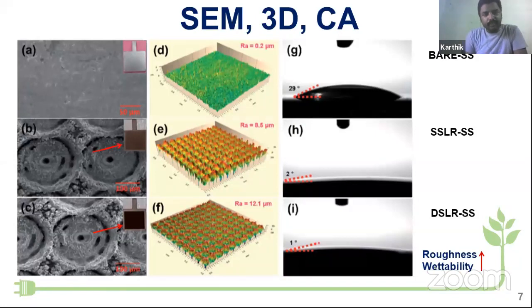Then D, E, F are the respective 3D images of the substrates. When we look at this, the surface roughness is increasing from 0.2 to 12.1. So when we irradiate the metal surface by means of laser, the surface roughness also increases. Simultaneously, the wettability is also increasing. We can see from figure G, which is for the bare stainless steel substrate, that the contact angle is about 29 degrees, whereas for single side it is about 2, and for double side it is about 1. So laser radiation is useful for creating rough texture as well as super hydrophilic texture.